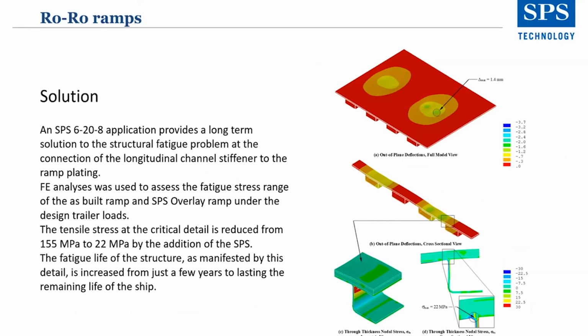FE analysis was used to assess the fatigue stress range. The tensile stress at the critical details was reduced from 155 megapascals to 22 megapascals by the addition of the SPS. The fatigue life of the structure, as manifested by this detail, is increased from just a few years to lasting the remaining life of the ship.